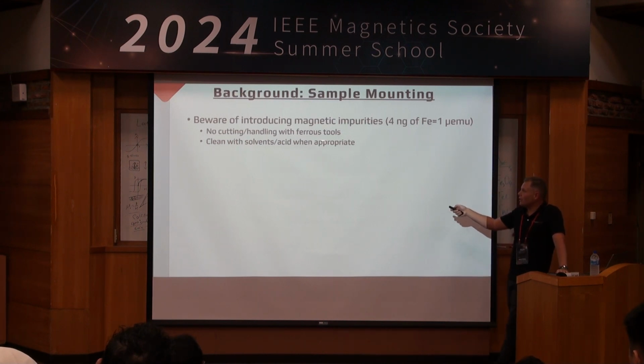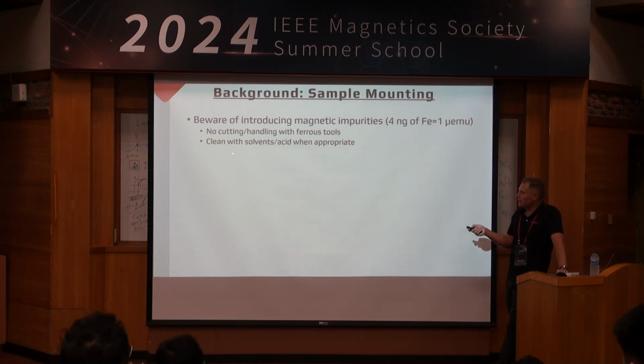So no cutting and handling with ferrous tools. Even diamond scribes can sometimes gall ferromagnetic material onto your sample. If appropriate, make sure to clean with solvents or acid. Obviously, if you have a metallic film on a silicon substrate, don't put it in acid. There goes your film, right? So have some common sense here.